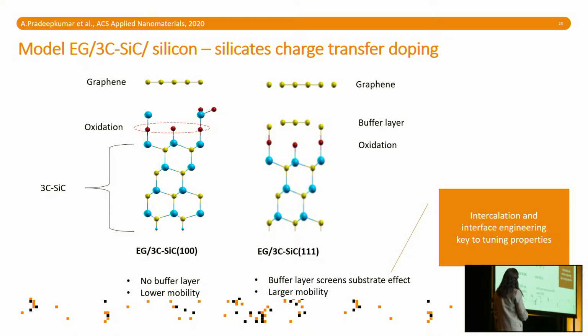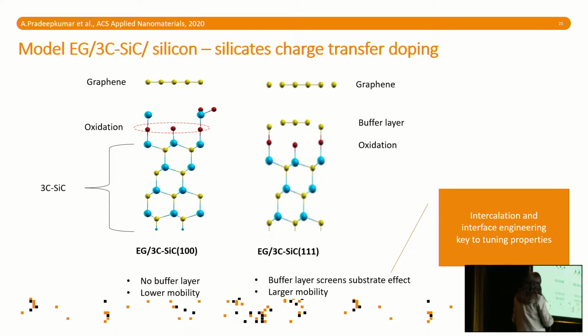Why is that different between these two phases? It is because on the 111, we actually can create a buffer layer. Remember that the 111 phase of the cubic silicon carbide corresponds basically to the hexagonal 0001, and they respond more or less in the same way, the same chemical situation. So we do form a buffer layer there. This acts a little bit as a screening. It means although we have oxidation here, this is slightly screened by this buffer layer onto the graphene. It means that we have slightly lower charge transfer, charge carrier density in this case, as the measurements have shown.